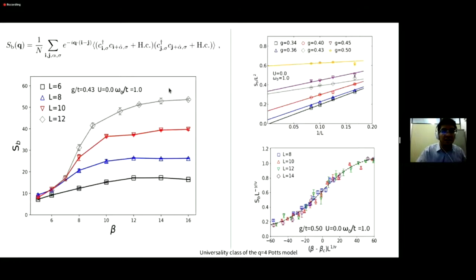So we analyzed the structure factor and how it behaves at zero temperature, as we provide here in this finite size scaling analysis. And also we obtained the critical temperatures here, providing a data collapse of these points using the universality class of the Q equals 4 Potts model. And so we could obtain, for instance, the critical temperatures.